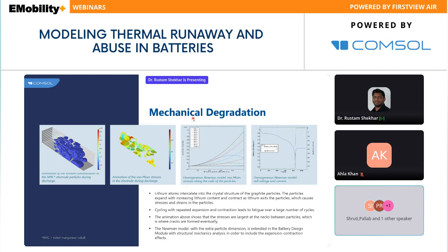So this mechanical degradation again will lead to more SEI formation, and then we are losing more capacity. So this capacity loss again will help to increase the IR losses, and those IR losses again will give you more degradation, and that will lead to more failure in the battery. So this is one more classical case.